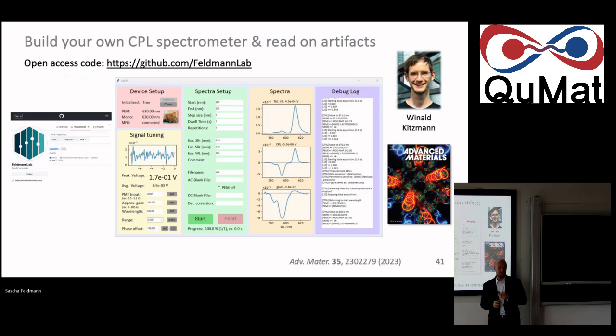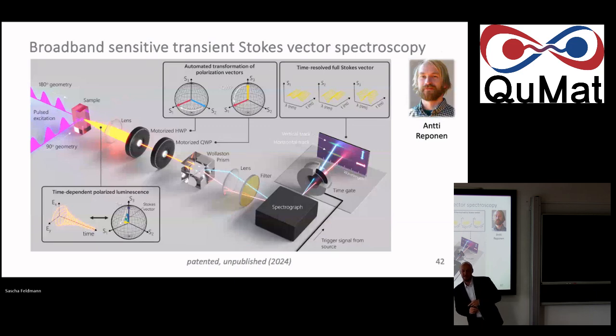So since then, and this is the very newest and last little outlook before I'm done, we have ventured on to really do transient CPL, which there isn't any good one, and we've really looked into the literature. You can easily just chuck in a quarter wave plate or so and hope for the best, which is all fine if we don't want to add the word sensitive. And also fine if we don't want to add the word broadband. We now talk about the full broadband visible spectrum, sensitive CPL spectroscopy. And sensitive means 10⁻⁴ dissymmetry factor, which is what a traditional, say, helicene chiral organic molecule would show you. And 10⁻⁴ is not something you can measure with just a rotating quarter wave plate.